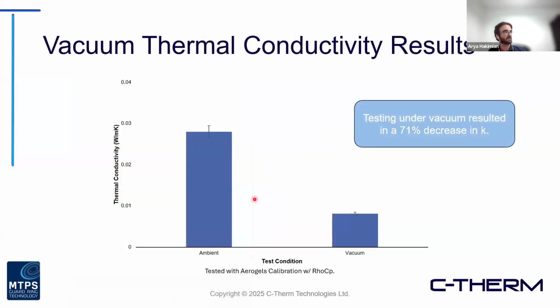And this was a test that we ran here, and you can actually see under ambient conditions with the MTPS, it was about 0.028 watts per meter Kelvin on the polyurethane foam. But then when we actually subject it to vacuum, we see a significant drop. So this, really hitting into that novel aerogels range, while inherently not being a traditional aerogel in that sense.